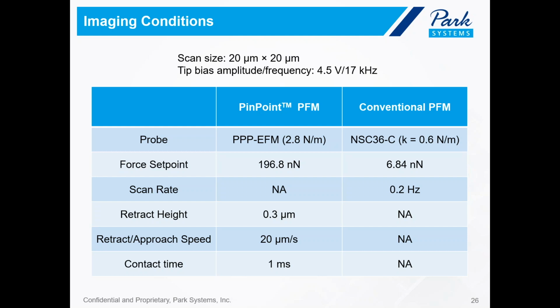So in PinPoint PFM imaging, we used a PPP-EFM cantilever, which has a nominal spring constant of about 2.8 Newton per meter, and this cantilever was coated with platinum to ensure its conductivity. The nominal radius of the tip curvature is about 25 nanometer, and the force set point used in this case is about 196.8 nanonewton. The retract height was 0.3 micron.